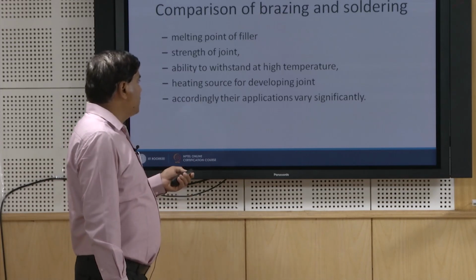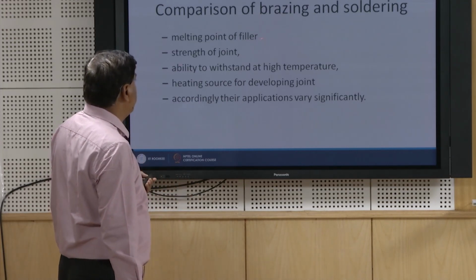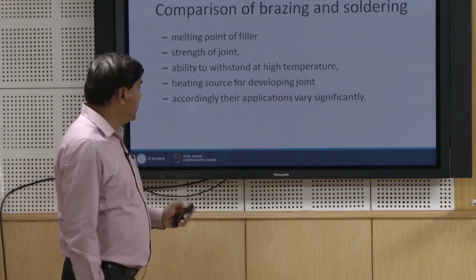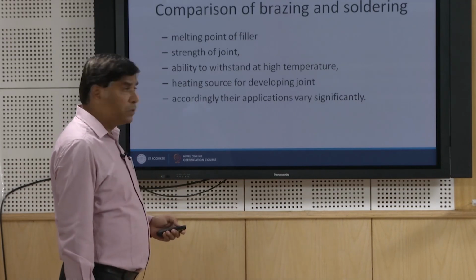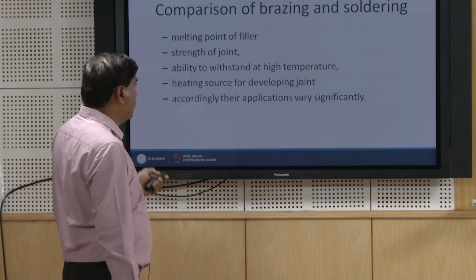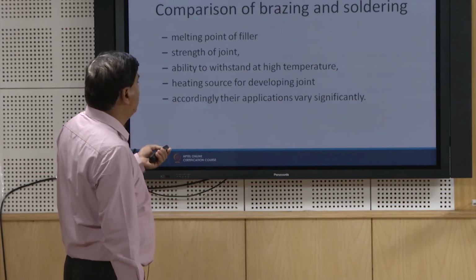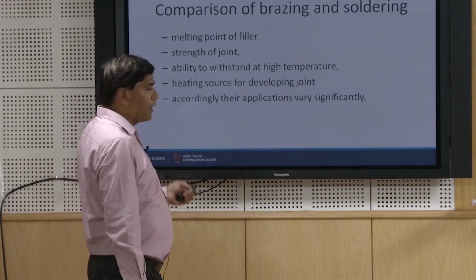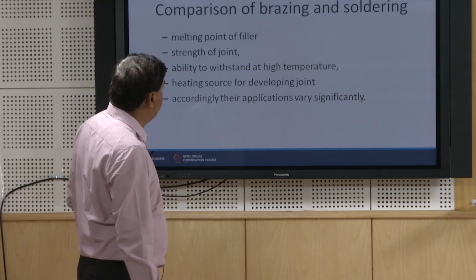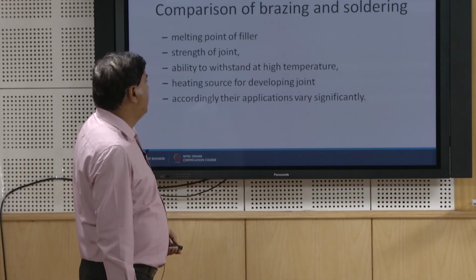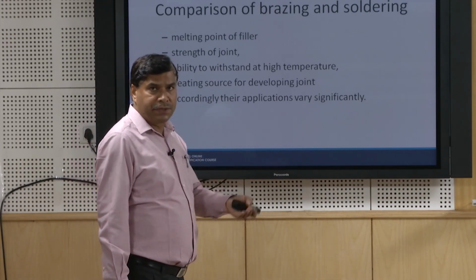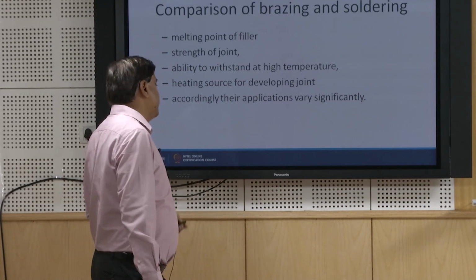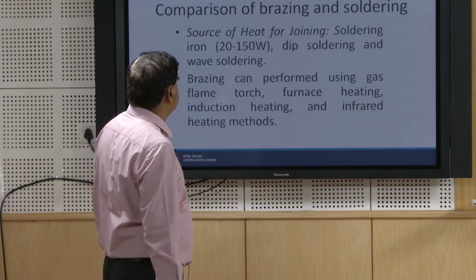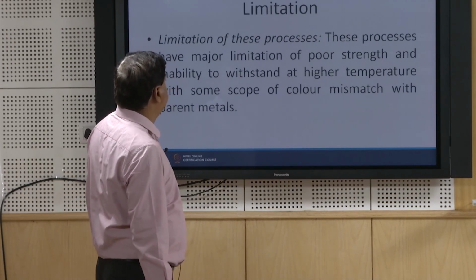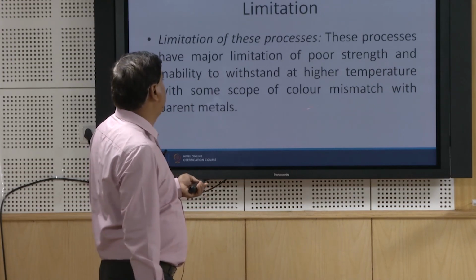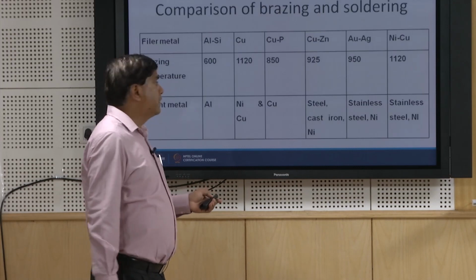These are the different points based on which brazing and soldering can be compared. The melting point of the filler is lower for soldering than for brazing. The strength of the braze joint is much higher than that of the solder joints, and the ability to withstand high temperature is better for brazing joints as compared to soldering joints. Heat source requirement means a higher capacity heat source is needed for brazing as compared to soldering. According to their load carrying capacity or ability to sustain higher temperature, these two processes find applications in different areas. So, this is just for comparison. Limitations of these processes are poor strength, inability to withstand high temperature, and sometimes color mismatch is another problem which is encountered.